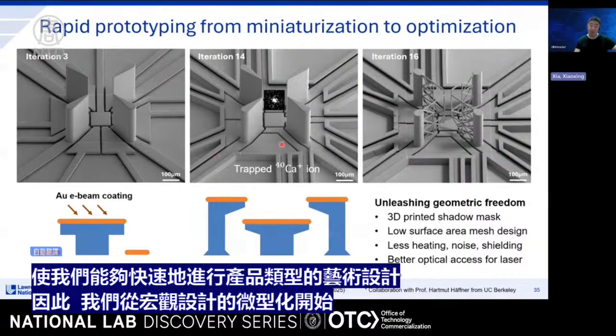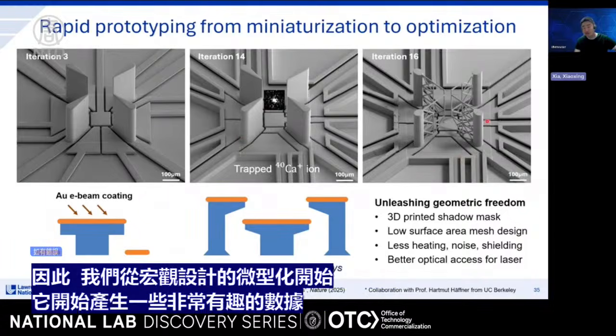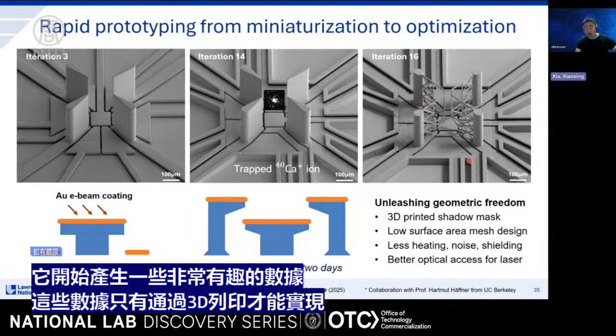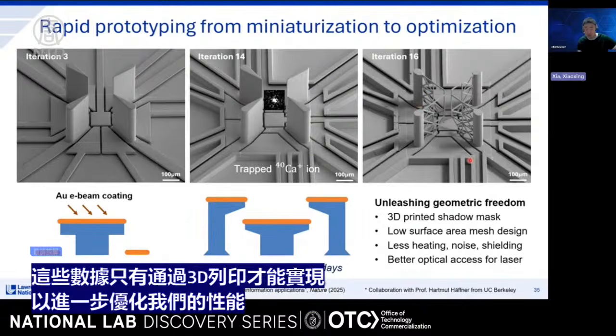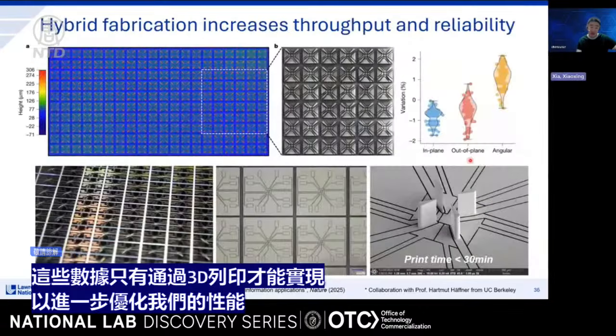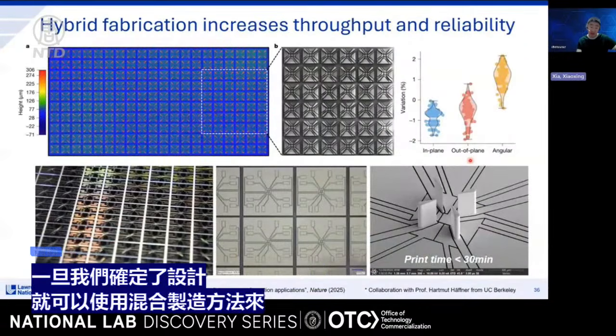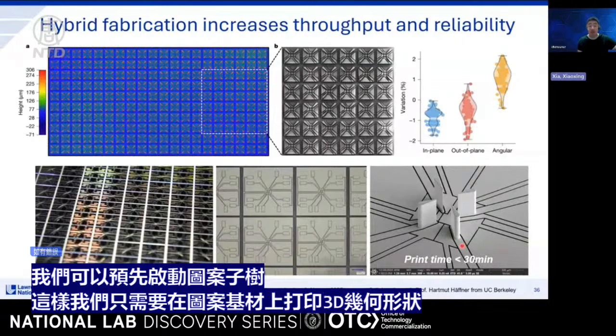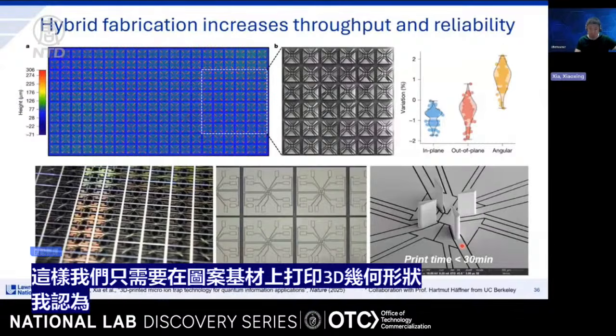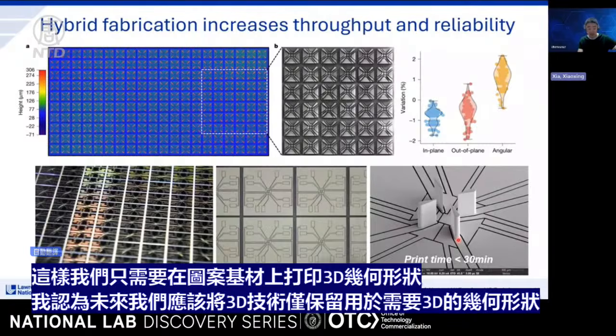So we go from just miniaturization to optimization, where it's starting to evolve some very interesting features that are only enabled by 3D printing, to further optimize our performance. And once we have settled on a design, we can use a hybrid manufacturing approach to make this process faster. We can prefab a patterned substrate such that we only need to print a 3D geometry on top of the patterned substrate. In the future, I think we should reserve 3D printing only for the geometry that needs to be 3D. And this will further improve the printing speed and increase the yield of our fabrication process.